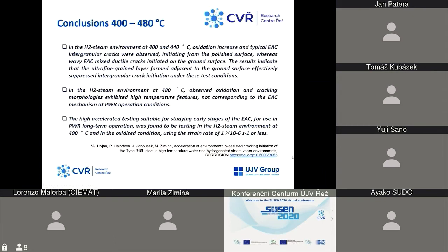So in this hydrogenated steam environment, the oxidation increases, and we see the typical intergranular cracks at both 400 centigrades and 440 centigrades. When we go to the higher temperature, we also observe oxidation and cracking, but these morphologies do not correspond to the mechanism which we usually observe at the PWR operation conditions. And so for highly accelerated testing suitable for studying early stages of EAC, we need to test at 400 centigrades.